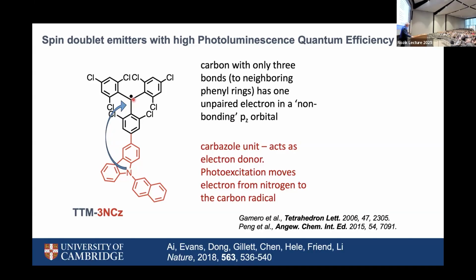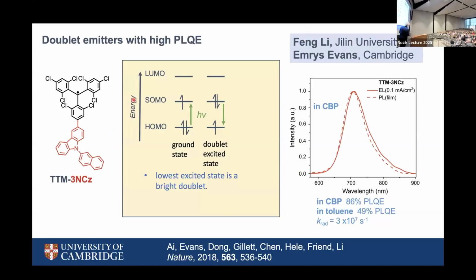And the spectrum quoted on the right, this particular molecule is just beyond red. It's quite far towards the near infrared. So in terms of energy levels, what we have is the HOMO level, the doubly occupied level, which donates an electron, is sitting on the carbazole. When we absorb a photon, we take one of those electrons and transfer it onto the radical or that excited state, and then it can emit down again. And it's bright. We have very high luminescence yields. They're heading towards 100% in many of the structures that we're now looking at. And there's no triplet.